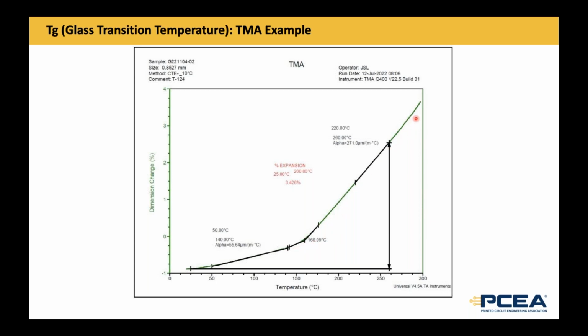are critical parameters. And the measurement of that is very accurate, at least for each sample, because of the way the machine works. It has a small stage with a highly calibrated, very precise monitoring of the Z-axis position of a quartz probe. That probe sits on the sample, and then as you heat up the chamber in a controlled way, it measures the position. There's a bunch of other steps in the procedure to make sure that works well. But you get a very accurate measurement of the Z-axis expansion over temperature.